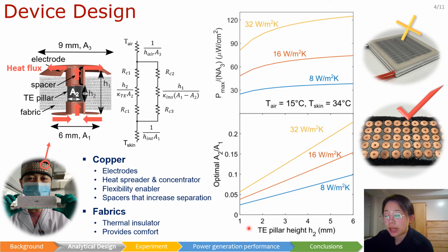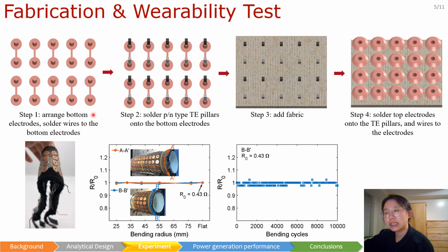By tuning the thermoelectric pillar height, area ratio A2 to A1, and the thermal environment parameters, we can obtain their relationship to the output power density, so we can find out the optimum configurations under different circumstances. In this slide, we show the 4-step fabrication process and some tests on wearability.